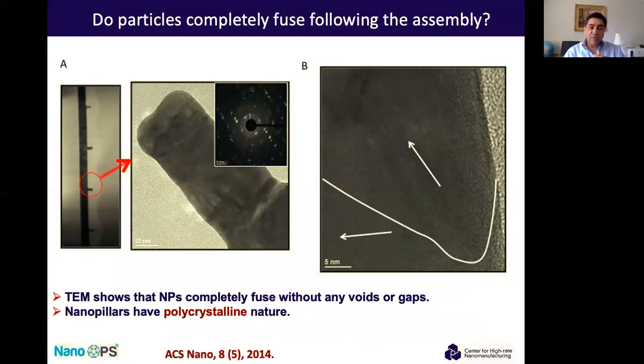And so when we looked at this, we found that this interconnect, this pillar, is about 50 nanometers in diameter and about 150 nanometers high. And when we took a cross-section, we found one grain boundary, and that indicates you have two, it's polycrystalline, so you have single crystal here and a single crystal here, for example. And this was done without any annealing, without any heating.